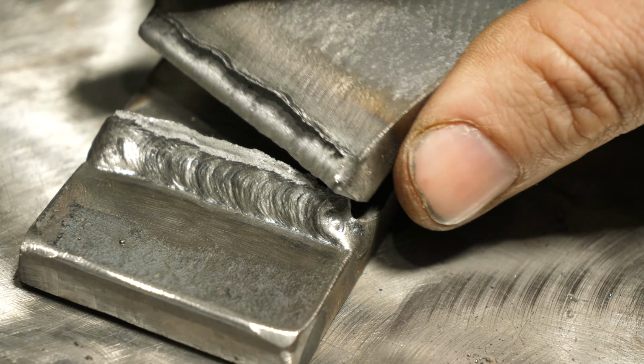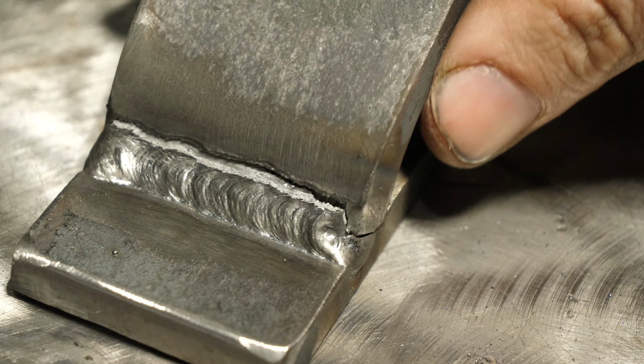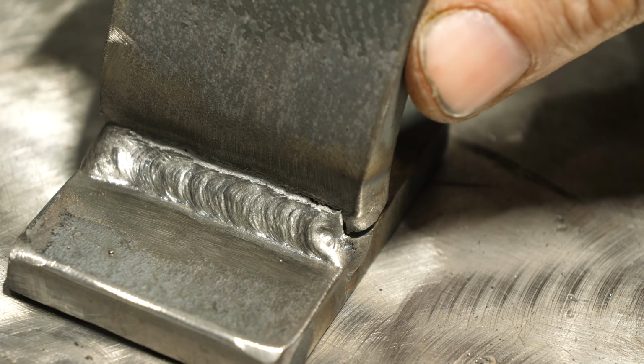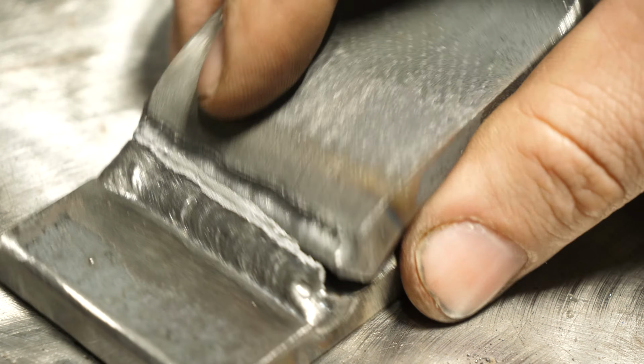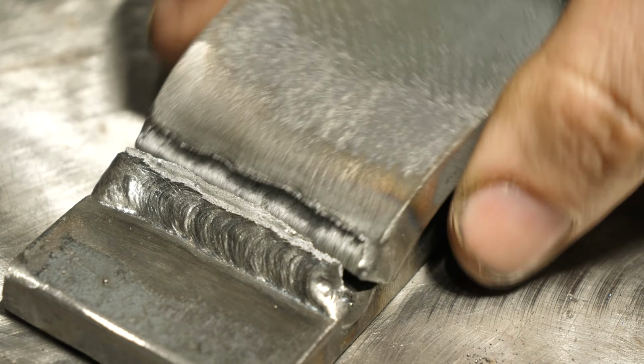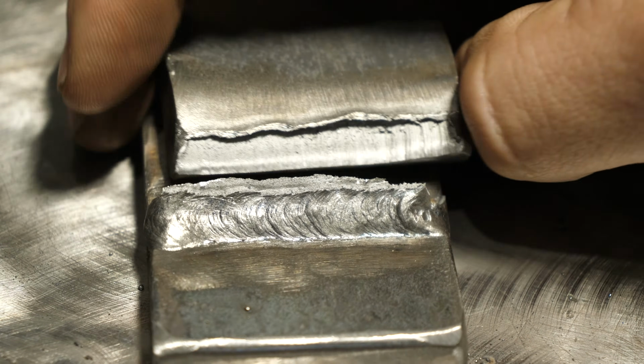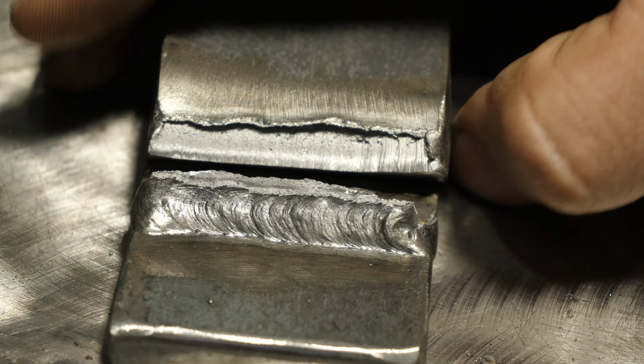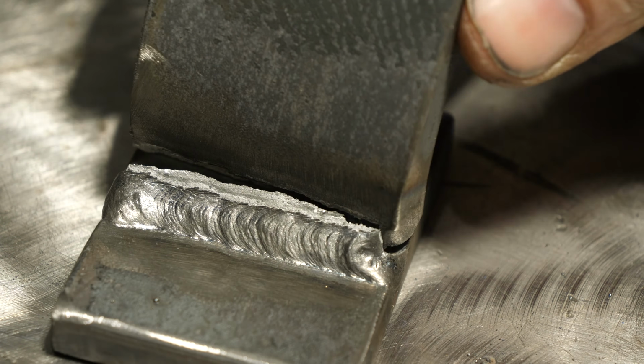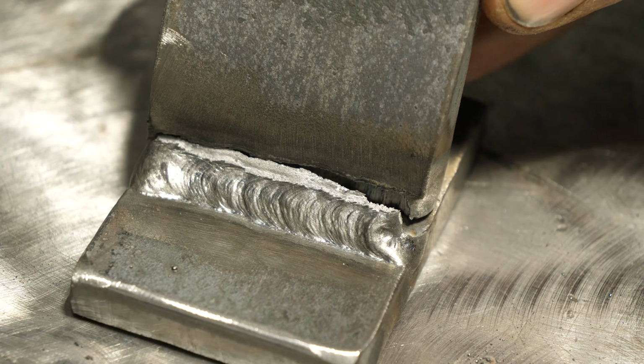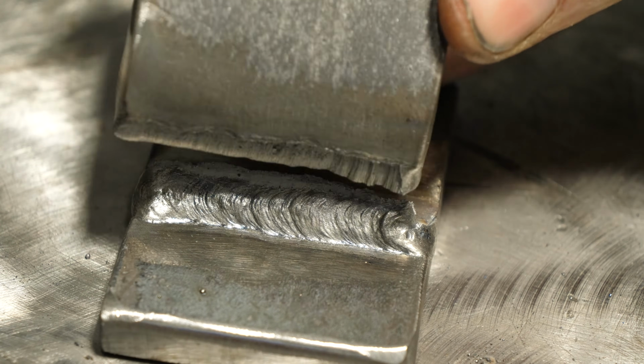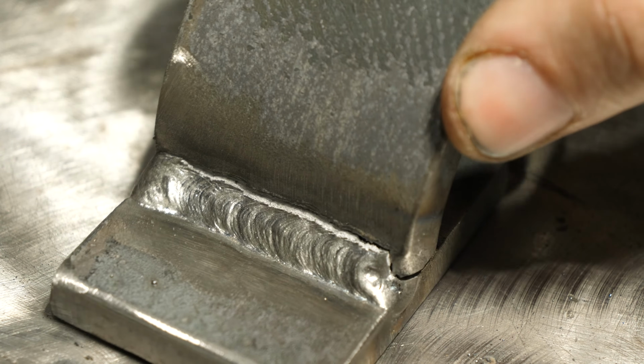I think what could have happened here is simply, by the look of it, I mean, maybe, it's hard to say though on the top. There was no undercut that I could see. I mean, I definitely picked the better of the two welds, and it is favoring a 45-degree angle, so that's correct. In this case, it's hard to say. I mean, it could have been a change where the weld metal met the base plate, and that change was more brittle than the base plate.